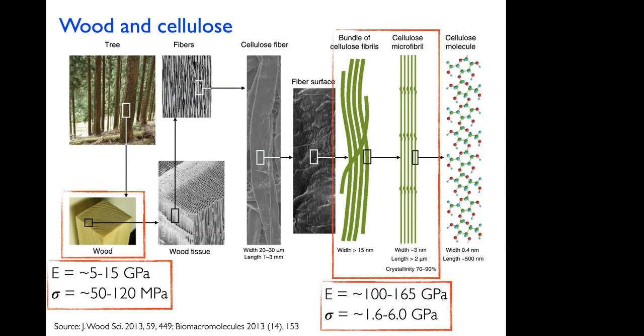In terms of strength, nanocellulose is about 1.66 GPa. Comparing to conventional glass fibers — which have an elastic modulus of only 72 GPa — these nano-scale cellulose fibers are actually twice as stiff as a single glass fiber. The strength of nanocellulose fibers is up to 6 GPa, whereas a conventional glass fiber is about 3 GPa. There is actually quite a lot of potential in utilizing these nanocellulose fibers to produce renewable materials, and for the rest of the presentation we will be focusing on that.